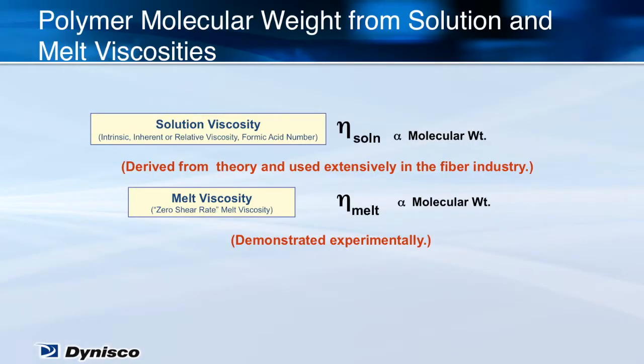Now that we have correlated the online melt flow index reading to our lab results, I want to talk about how we can use this information to report an IV value. It is really useful to monitor the IV online rather than in the lab, especially since the IV test requires the use of solvents. Dynisco has developed software that provides excellent correlation of the standard capillary data to the intrinsic viscosity of PET. This feature has generated interest among PET compounders and processors. We do this on both laboratory melt flow indexers and online rheometers.